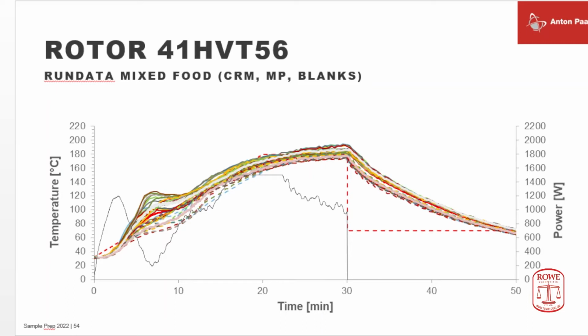The important thing is that you take all your samples to the desired end temperature of 180 degrees, because within this period of time the final mineralization takes place. So no matter how the course of the reaction is at the beginning, at the end all these 41 samples achieved the same desired end temperature. Then you see it's about 15 to 20 minutes to cool down. This is what you get to see on the screen of the instrument after the digestion.